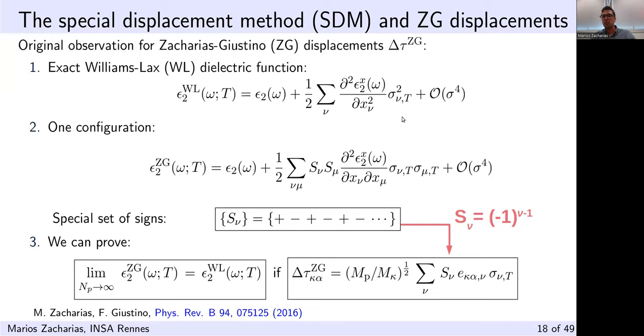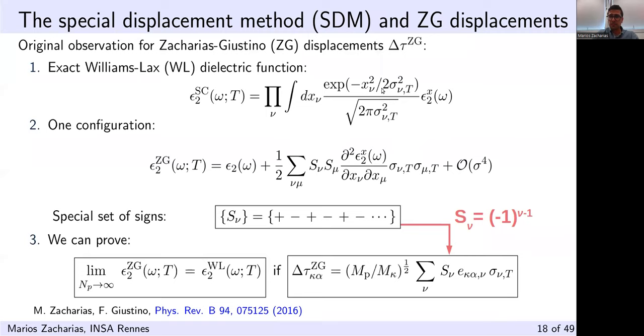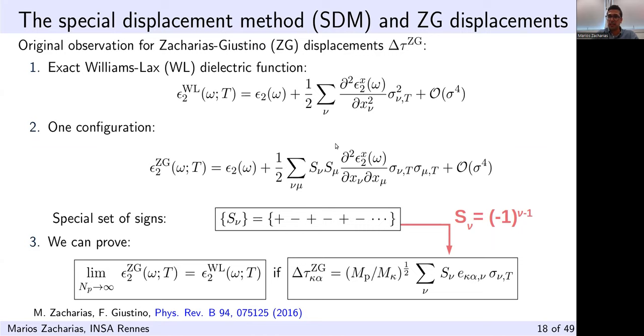The difference between the exact and the single-configuration result lies in cross-coupling terms for different phonon modes entering the second-order coefficients. The trivial choice is to place all phonon modes in energy order and alternate signs plus/minus. In the limit of a large supercell, consecutive coefficients will be very similar, enter the summation with different signs, and cancel each other, reproducing the exact Williams-Lax dielectric function. In our 2016 paper we proved that these ZG configurations give the exact Williams-Lax result.